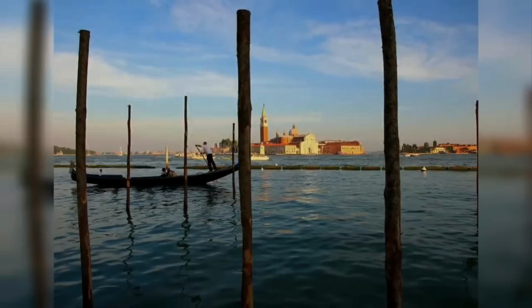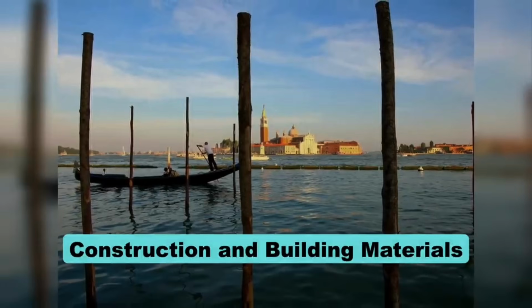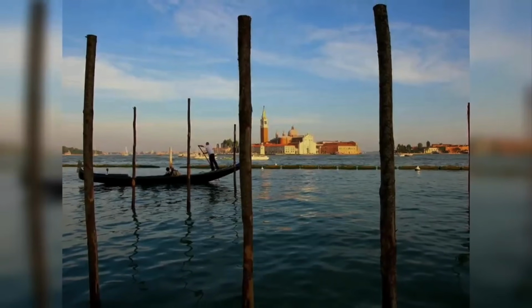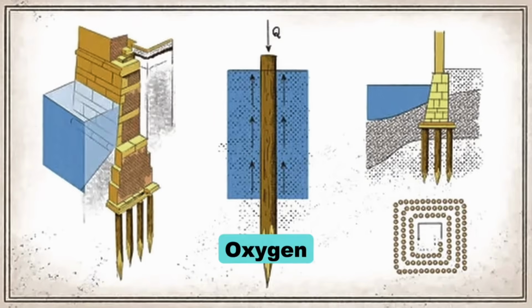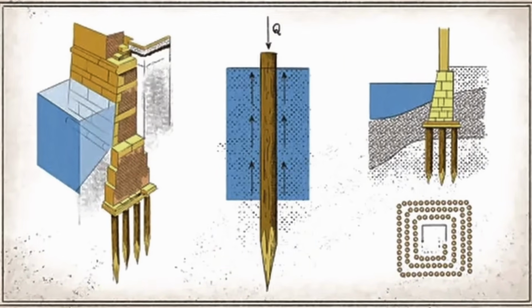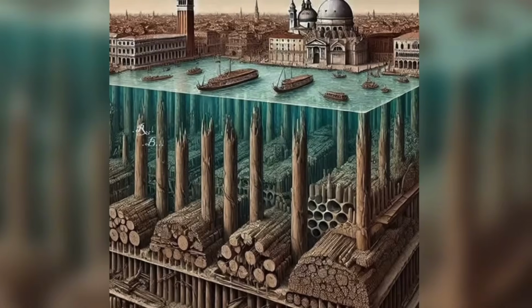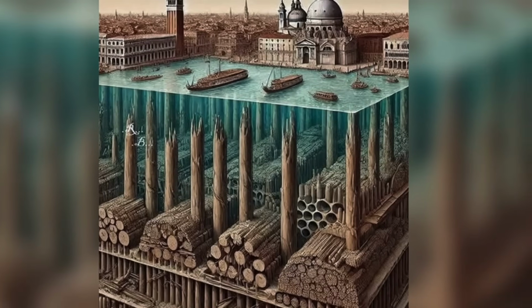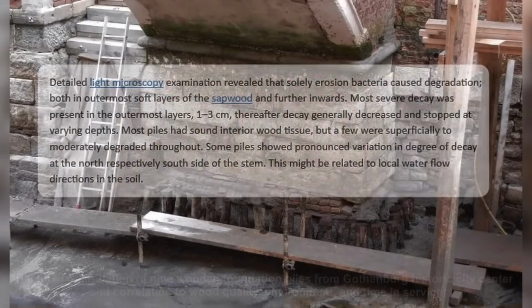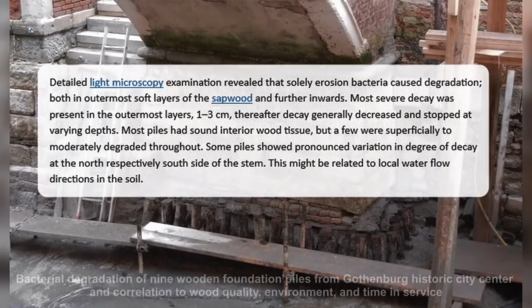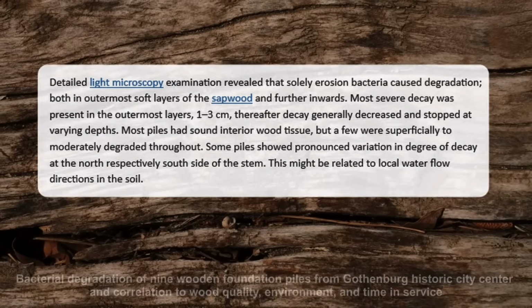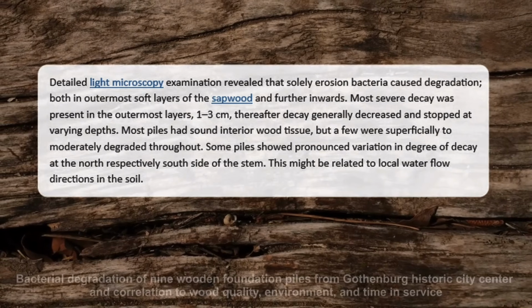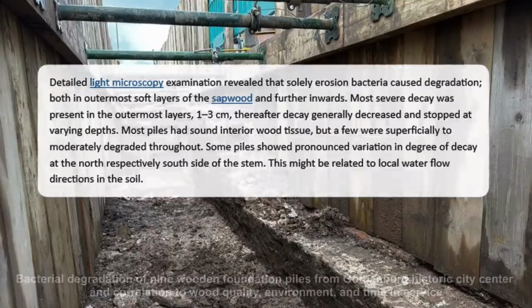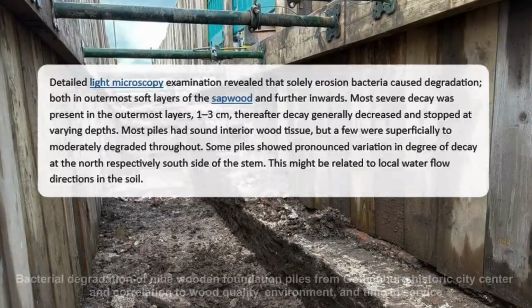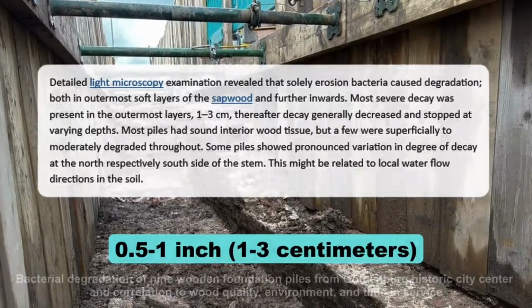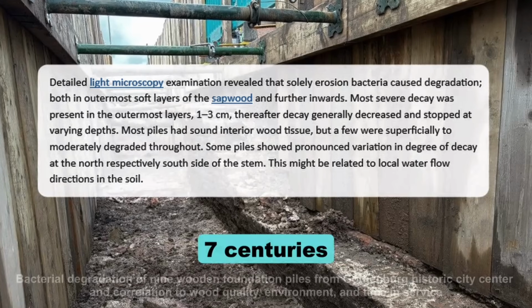A 2016 study published in Construction and Building Materials analysed woodpile samples from Venice's foundations and found that oxygen in the saturated lagoon sediment falls essentially to 0. Every rot fungus and aerobic bacterium that would normally eat the pile is starved. What remains is a single slow degradation pathway, anaerobic erosion bacteria that attack the outer cell walls at a rate so gradual that medieval piles show bacterial damage in only the outermost half-inch to inch, 1 to 3 centimetres, after 7 centuries underground.